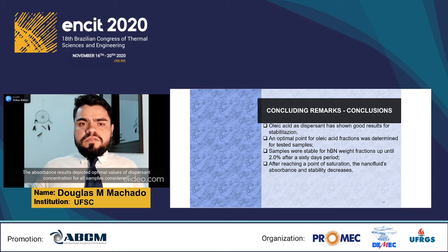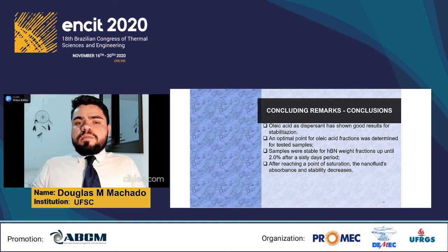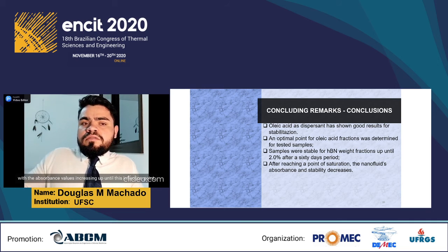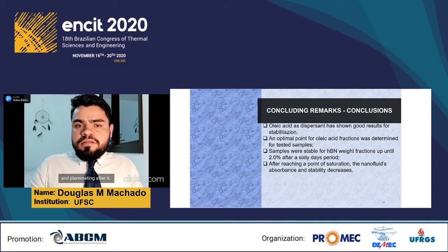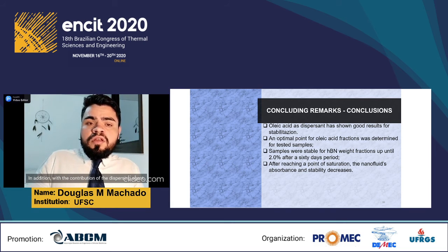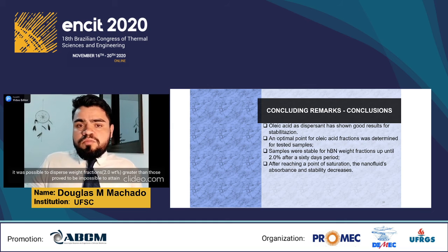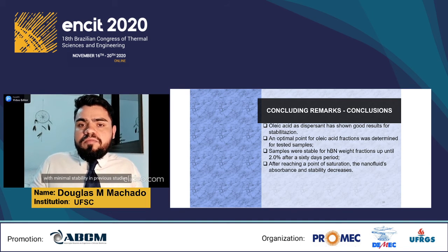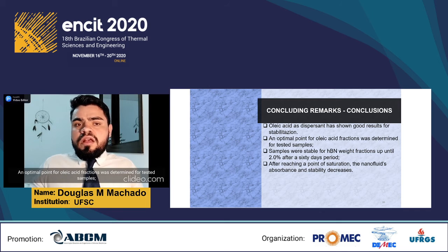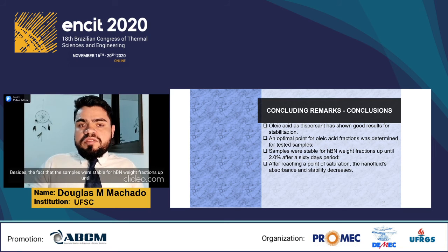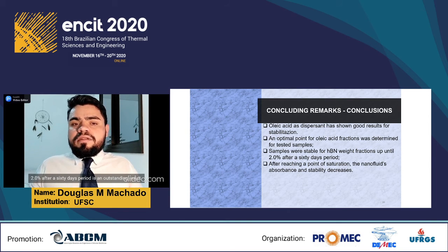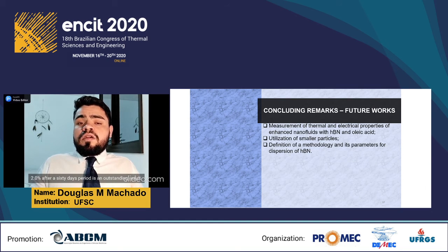The absorbance results depicted an optimal value of dispersant concentration for all samples considered, with the absorbance value increasing up until this inflection point and plummeting after it. In addition, with the contribution of the dispersing agent, it was possible to disperse weight fractions greater than those proved to be impossible to attain with minimal stability in previous studies. An optimal point for oleic acid fractions was determined for the tested samples. The fact that the samples were stable for hBN weight fractions up to 2% after a sixty day period is an outstanding result.